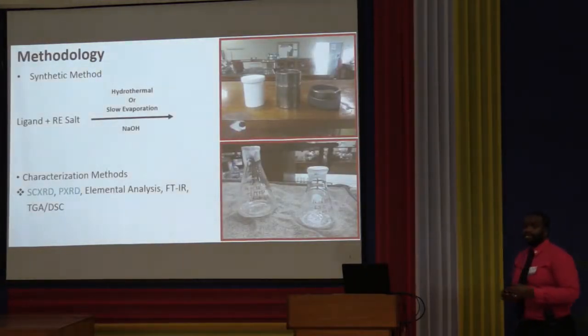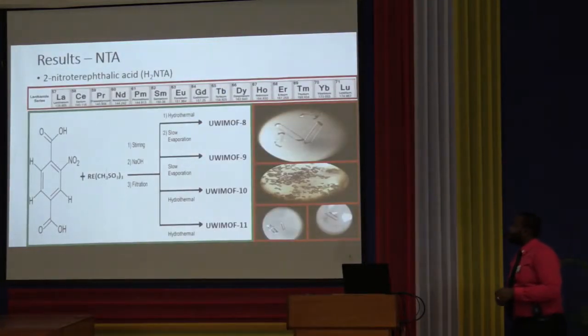Our methodology involves mixing the ligand with the rare earth salt and exposing it to hydrothermal conditions in a Teflon-lined autoclave, which is then placed in an oven at approximately 180 degrees C, or exposing it to slow evaporation conditions in conical flasks. The characterization methods include single crystal X-ray diffraction, which allows us to see the connectivity of the components, metal ions and ligands, in our structure, as well as powder X-ray diffraction, elemental analysis, FTIR, and TGA/DSC analyses. When we use the NTA ligand, which is 2-nitroterephthalic acid, we obtain 9 compounds with 4 different structural types, as you can see here. We use varying conditions, either hydrothermal or slow evaporation, and we could see an effect of the lanthanide contraction as well as reaction conditions on the formation of our structures.